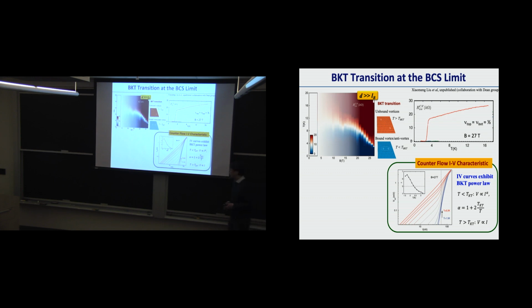It's a nonlinear power law behavior, and this power law exponent will tell us what is the transition temperature, or the vortex binding and unbinding temperature expected. And we can actually extract another energy scale, which is basically this BKT, KT transition temperature.